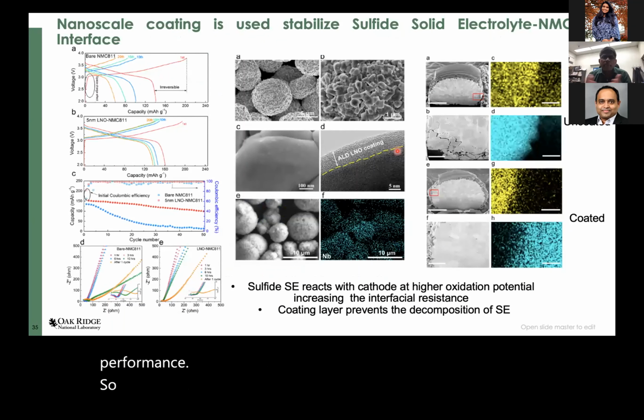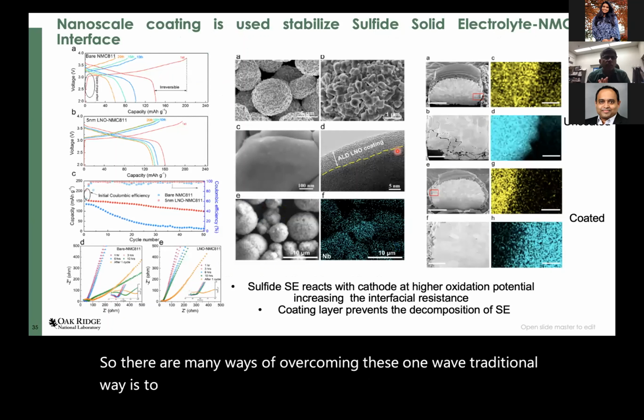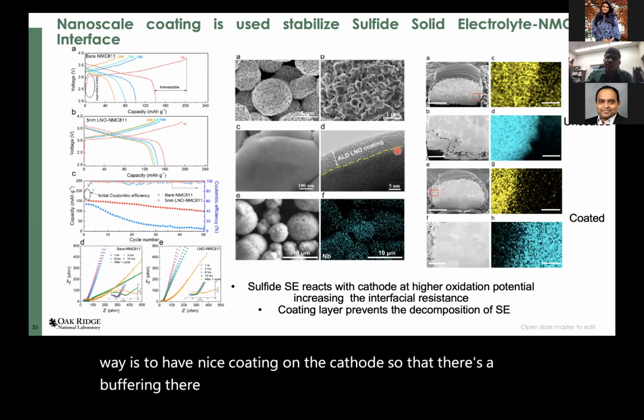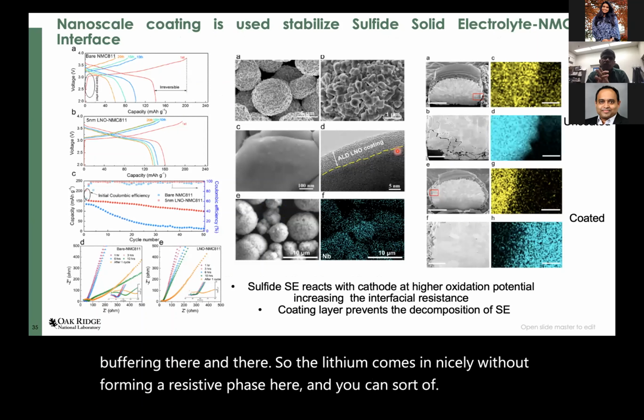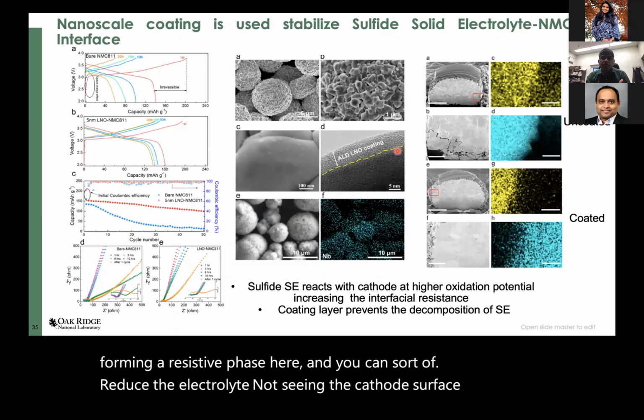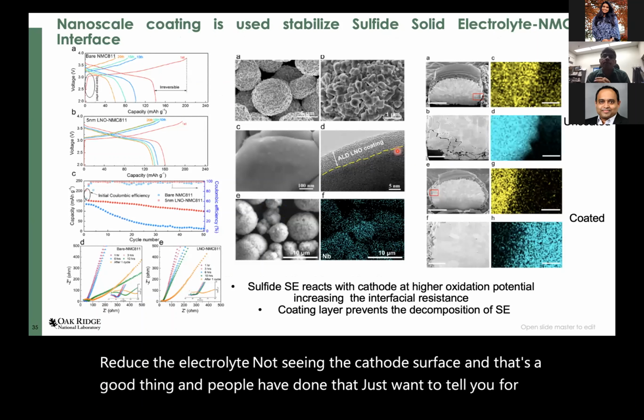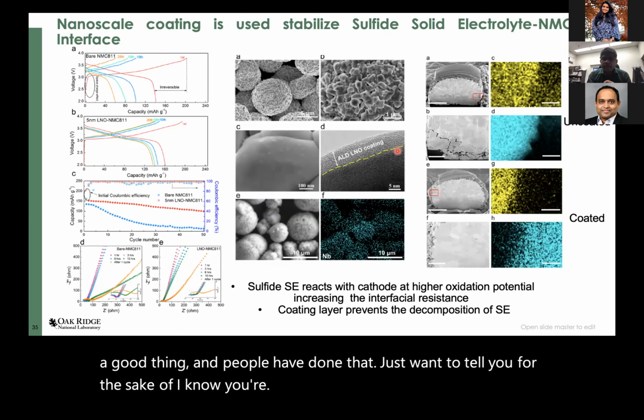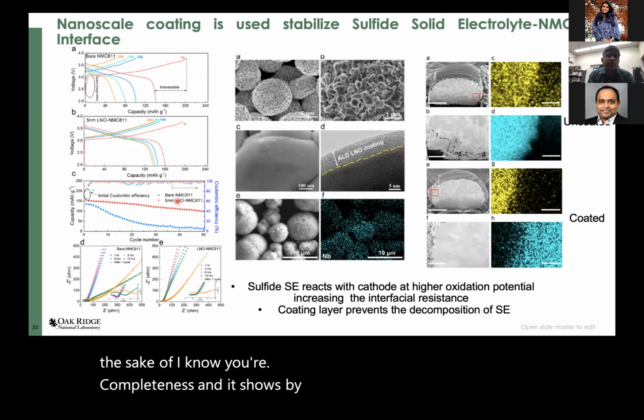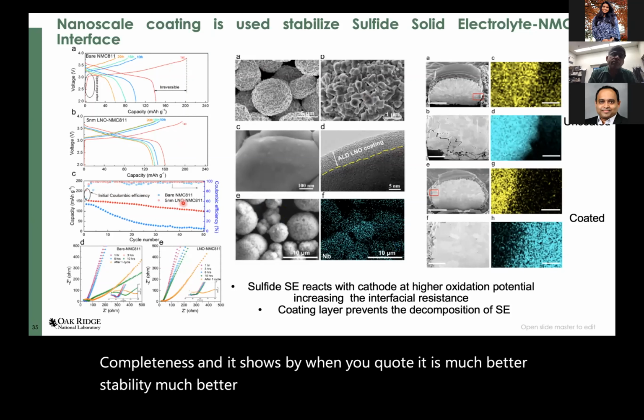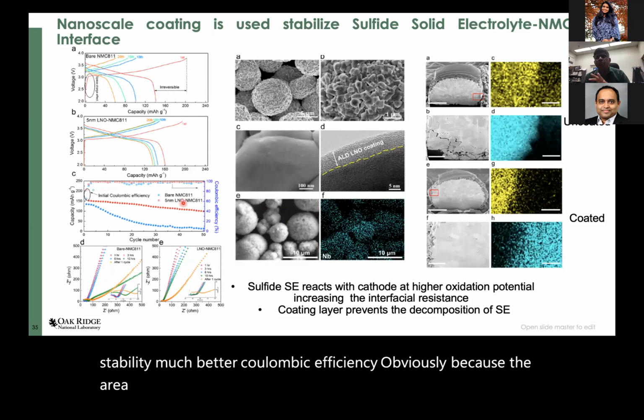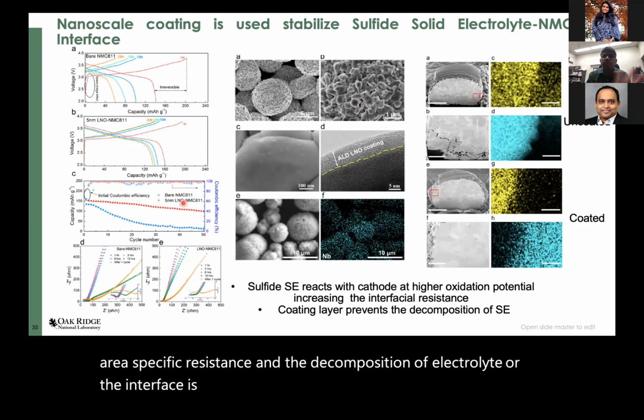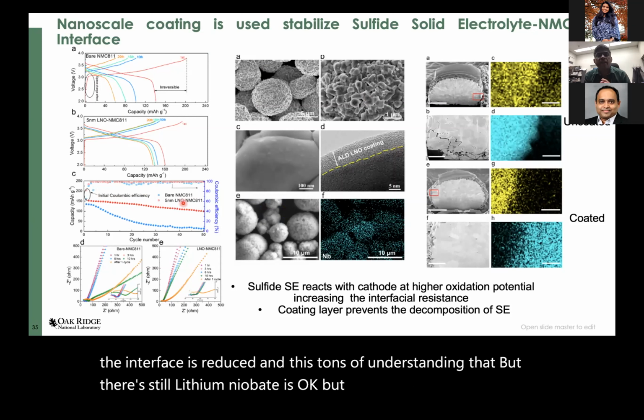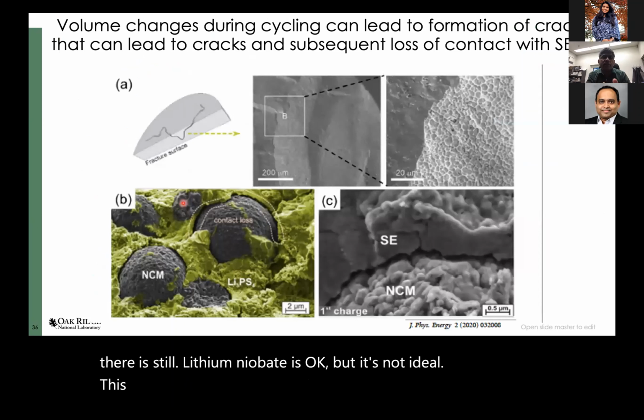So there are many ways of overcoming this. One traditional way is to have a nice coating of the cathode so that there's a buffering there, and the lithium comes in nicely without forming a resistive phase, and you can reduce the electrolyte seeing the cathode surface. That's a good thing, and people have done that. Just to tell you for the sake of completeness, when you coat it, there is much better stability and much better coulombic efficiency, obviously, because the area specific resistance and the decomposition of the electrolyte at the interface is reduced. There's tons of understanding of that, but lithium niobate is okay, not ideal.